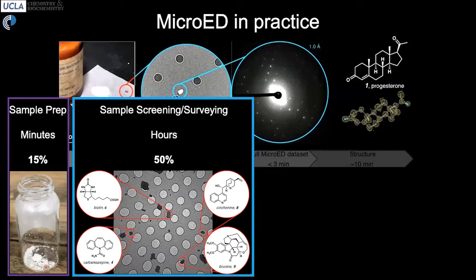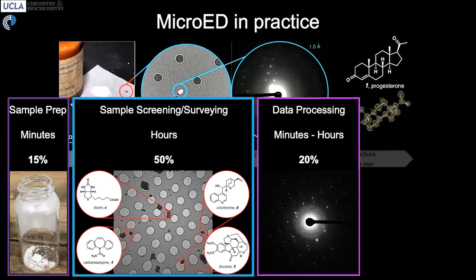And so some time is spent surveying, trying to figure out, okay, is this something that I'm interested in on the nanoscale? And you can see, for example, on this particular grid, there are a variety of specimens, and you would have to diffract from various ones to try to understand which ones you're actually interested in collecting data from. And this could take minutes, hours, or longer. And so once you've identified a sample of interest, you would diffract from it using the electron microscope. This would take some time and maybe minutes to collect a movie, but you might not be satisfied with a single movie from a single individual sample on your grid. So you might have to collect from various samples, collect a movie from each, and spend more time surveying. And so that could escalate the amount of time required for data collection and processing.